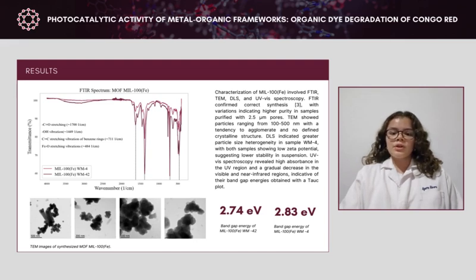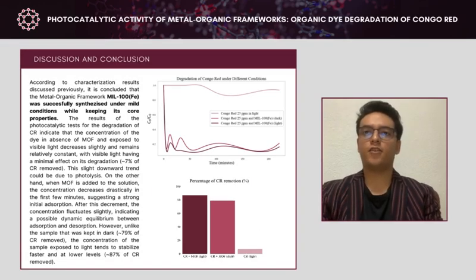With UV spectroscopy, the bandgap energies of both samples could be determined using the Tauc equation, performing a Tauc plot and extrapolating the linear region. Both materials show a high absorbance in the ultraviolet region and a gradual decrease in the visible region. According to the characterization results discussed previously, it is concluded that the metal organic framework MIL-100(Fe) was successfully synthesized under mild conditions while keeping its core properties.